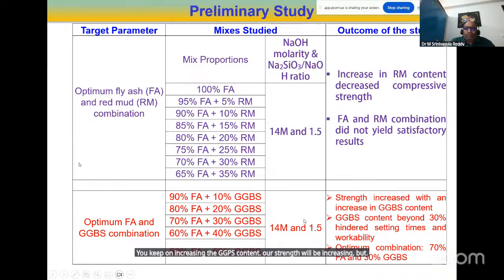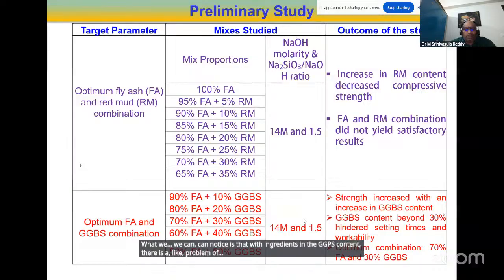But what we can notice is that with the increase in the GGBS content, there is a problem of faster setting. So in order to have reasonable setting times, we should restrict the GGBS to 30% only. In fact, even if you reduce it to 20%, it will be good, because with more GGBS content the setting sometimes takes place even before 1 hour. Even if you add so much plasticizer, it still does not stop the setting. So the optimum I consider in this study is 70% fly ash and 30% GGBS.